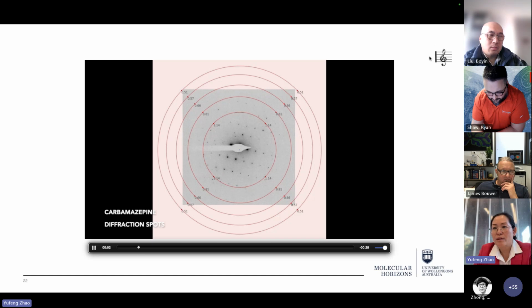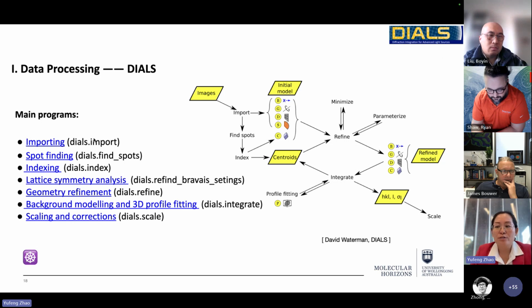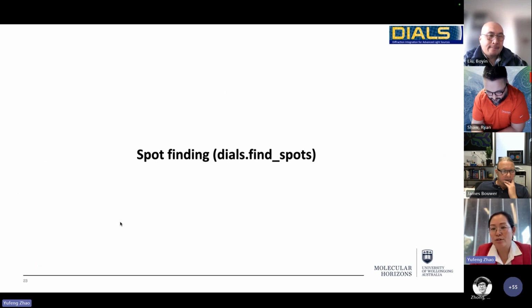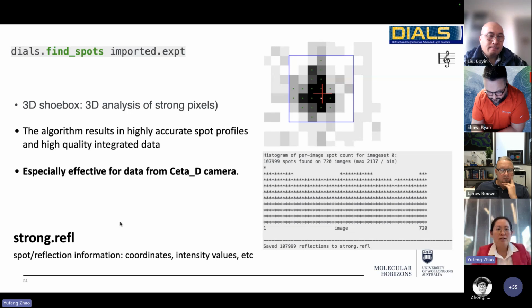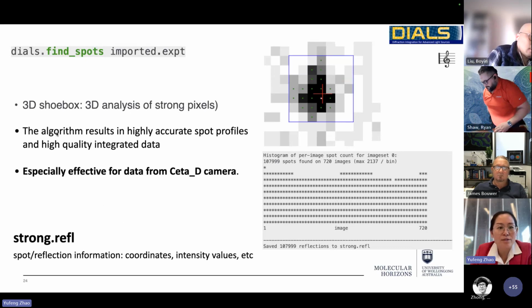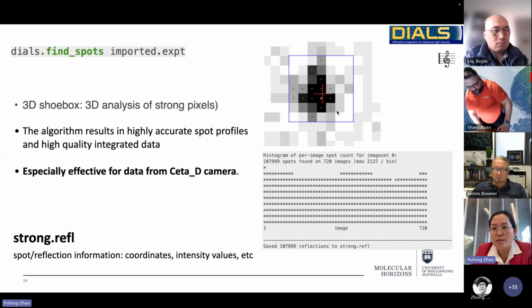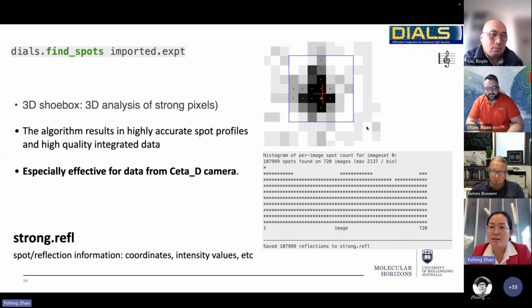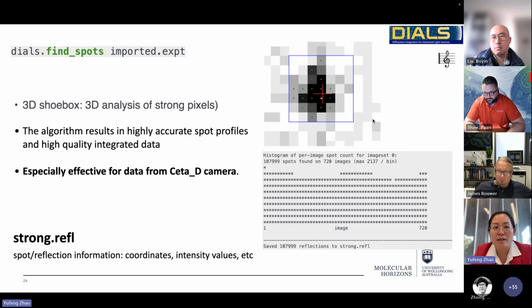So here's an example of our data after importing. After we do the importing, second, we need to find the strong reflection spots. So the DIALS find spots program does a 3D analysis of all the strong pixels. It picks up all the peak pixels, the strongest pixels, and gives us a 3D shoebox. From the shoebox, we can see the highest peak pixel and the centroid of this spot. And the algorithm currently is really accurate and gives us high quality data later. And it's especially effective for data from Ceta_D camera.